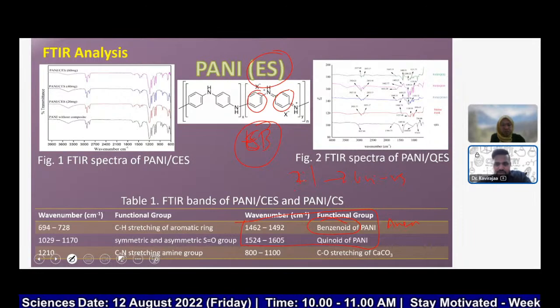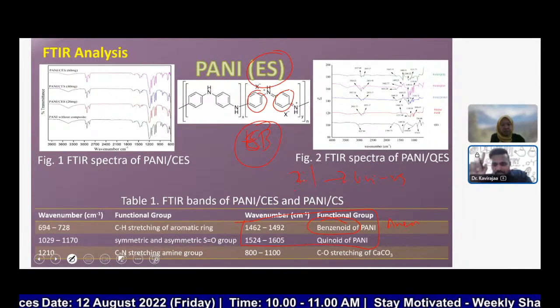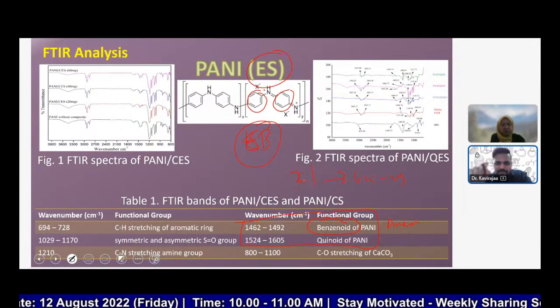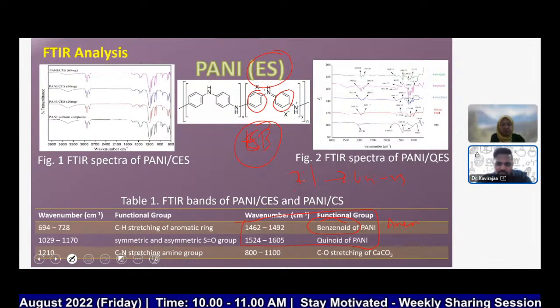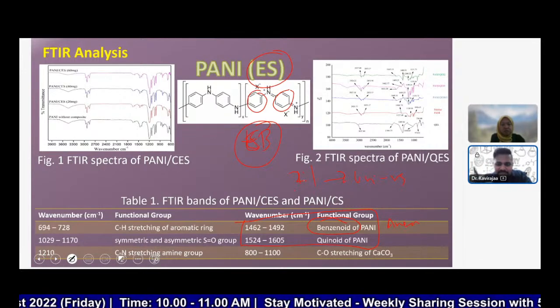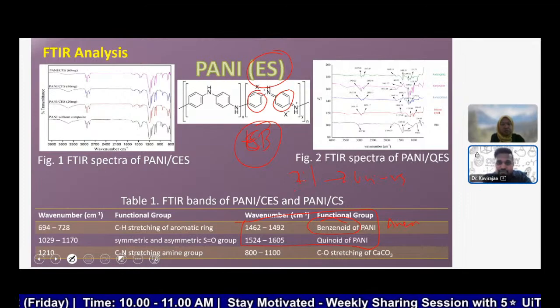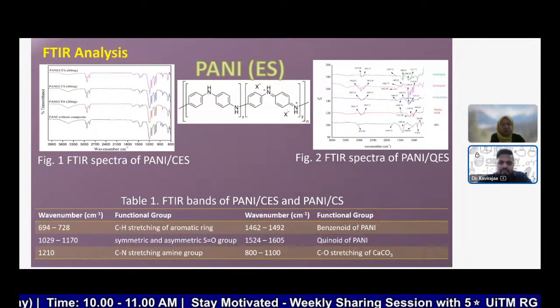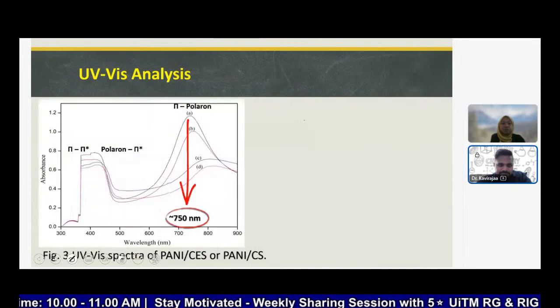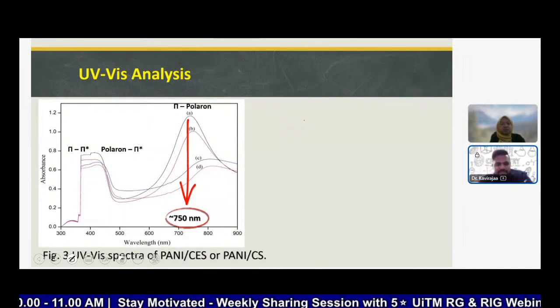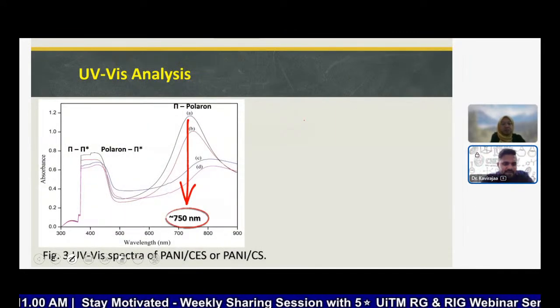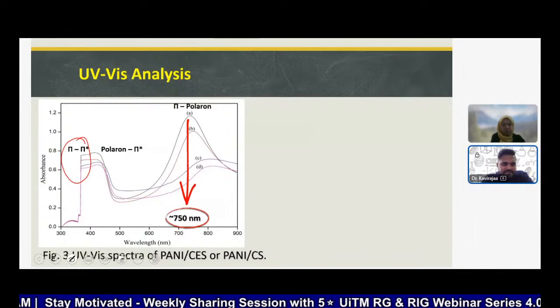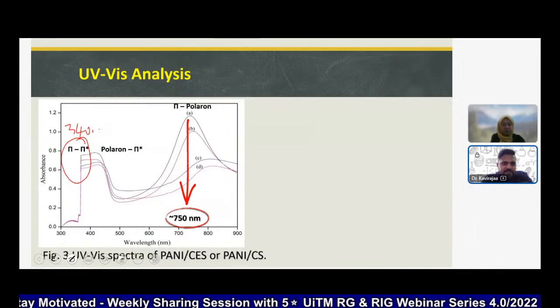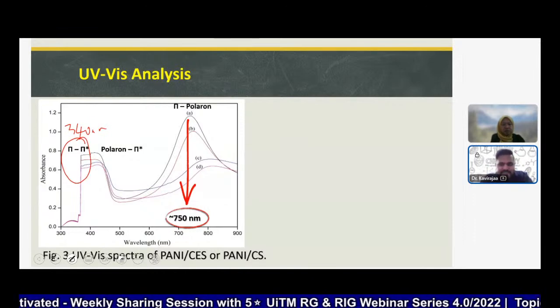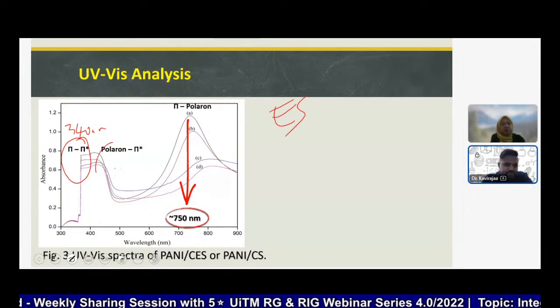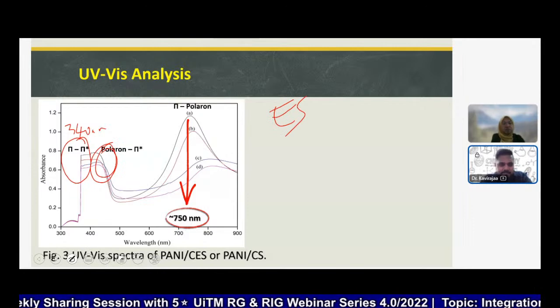conducting polyaniline or not. Okay, so here we got one problem, right? Even though we know that if we get a 1 to 1 ratio, it is in the emeraldine form, whether it is emeraldine salt or base, we can confirm by looking at the UV-Vis. So here there are three typical peaks. One is a pi to pi star peak, which is around 340 nanometer. And then normally, if it is ES, it will have this shoulder peak. It's like a characteristic peak.